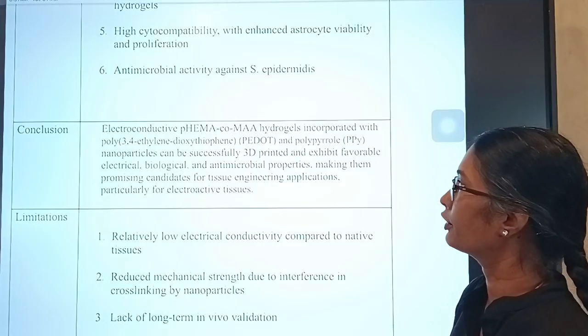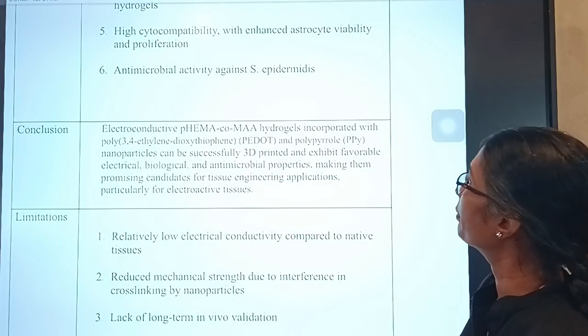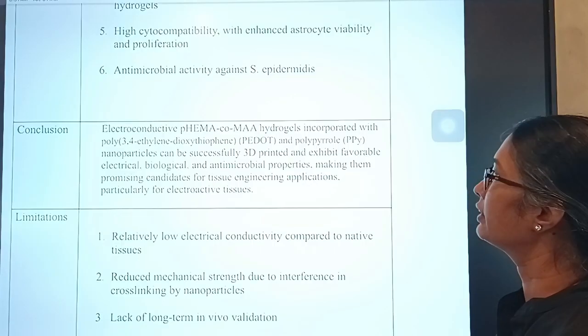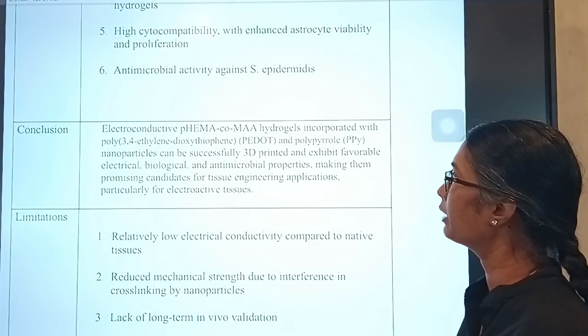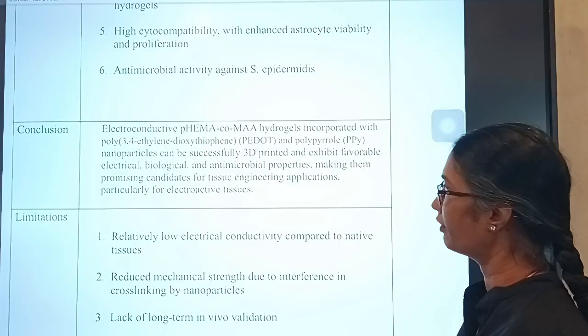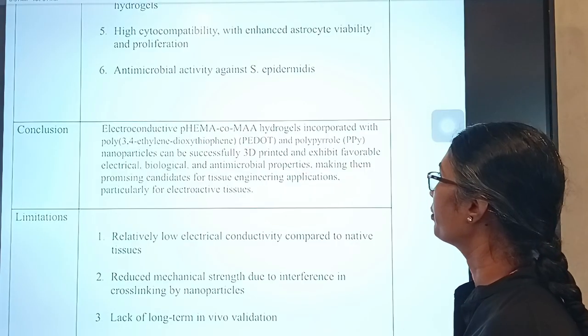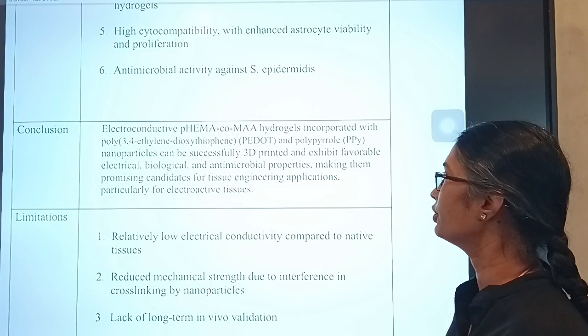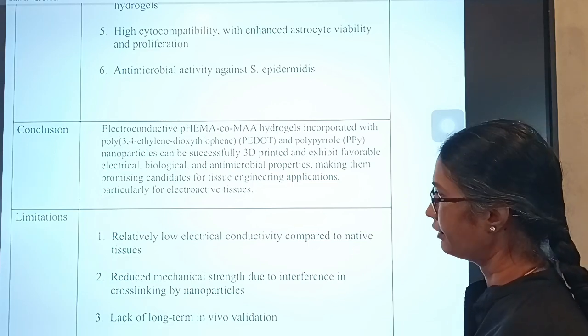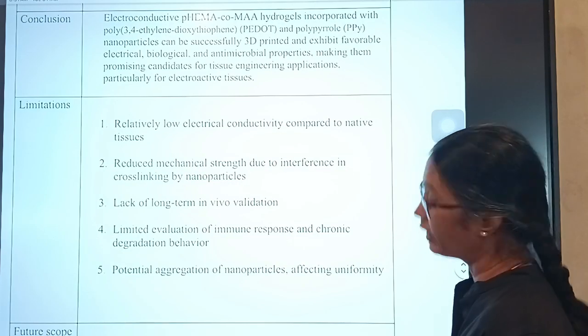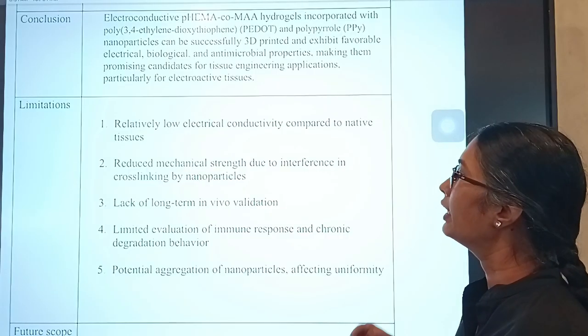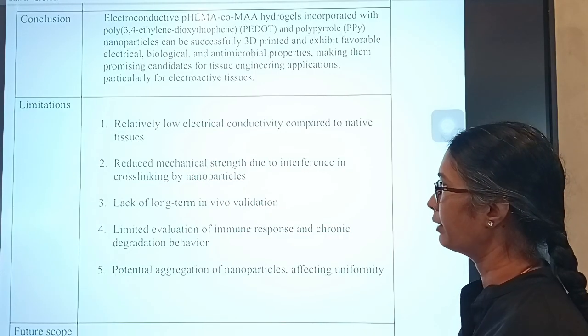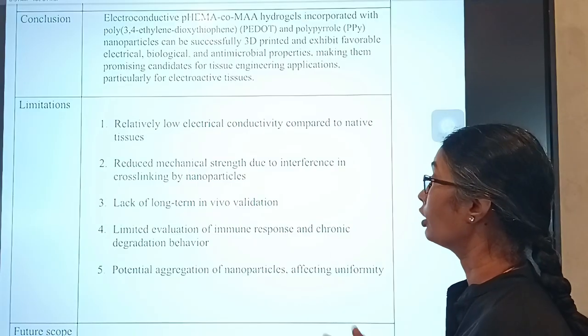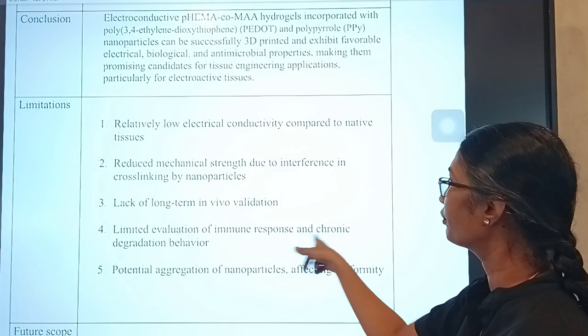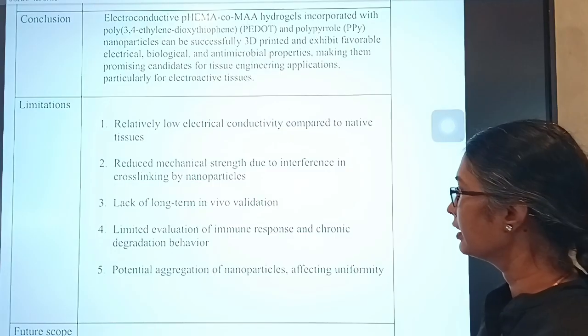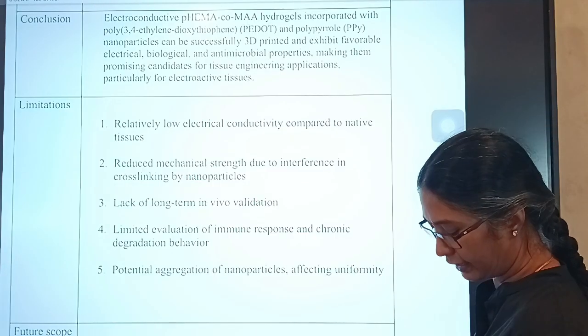So the conclusion was that the electroconductive HEMA-MAA copolymer hydrogels incorporated with PEDOT and PPy nanoparticles can be successfully 3D printed and exhibit favorable electrical, biological and antimicrobial properties, making them promising candidates for tissue engineering applications, particularly for electroactive tissues. Limitations included low electrical conductivity compared to native tissues, reduced mechanical strength due to interference with cross-linking by nanoparticles, lack of long-term in vivo validation, limited evaluation of immune response and chronic degradation behavior, and potential aggregation of nanoparticles affecting uniformity.